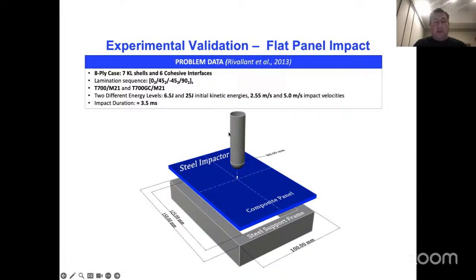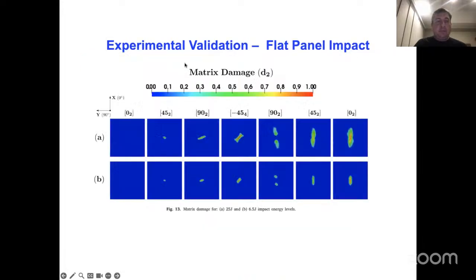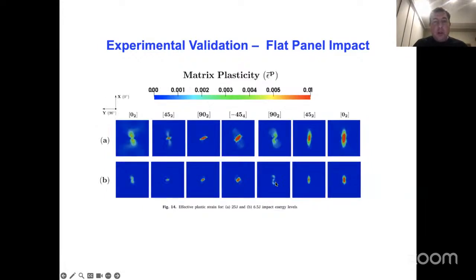So here's a frame. Here's our composite panel. Here's the impactor. So here's the matrix damage. On top is for the higher energy impact. Bottom, lower energy impact. Here's a distribution of matrix plasticity. And so you can see that while the magnitude of the effective plastic strain is not very high, you do see a fairly pronounced effect.